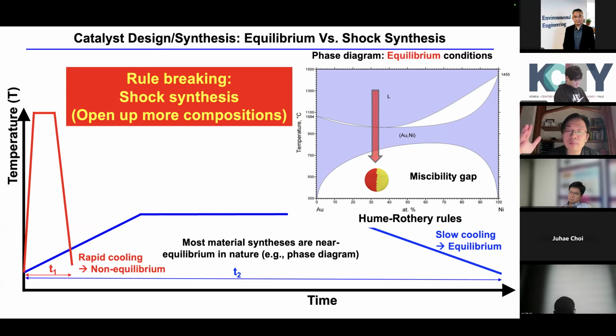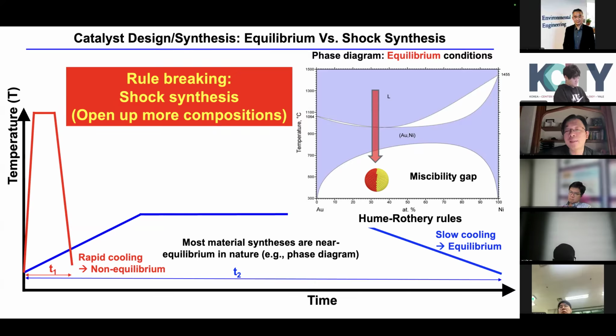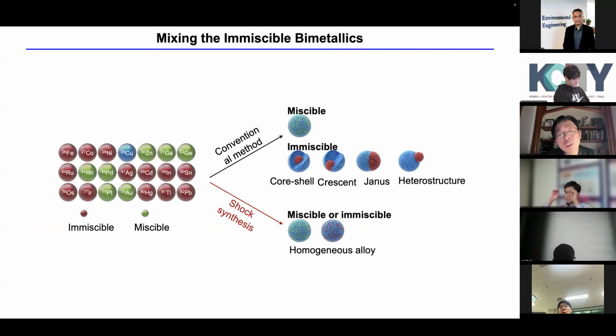In the phase diagram, at high temperature, the phase diagram is very simple. Everything is mixed. And you just quench it very quickly, as fast as you can. Then you can maintain the mixing that you have at the high temperature, right? So you can maintain the mixing that usually they will separate. So that is shown here, look at the right side. You see that with the conventional method, they will separate, they will be immiscible.